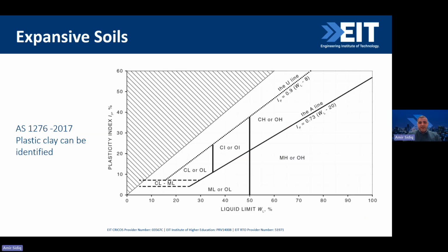So graphically, using the Australian Standard 2870 from 2017, we find the liquid limit, and then we calculate the plasticity index, and then we find which classification this particular clay falls into. If it's CH, it's a highly reactive clay. If it's intermediate, it's an intermediate reactive clay. If it's low, then it's a low reactive clay. So this provides us where we're sitting. For CH clays, we have a pretty high liquid limit and a pretty high plasticity index. We can straight away see that if we have a high plasticity index, it is an expansive soil.